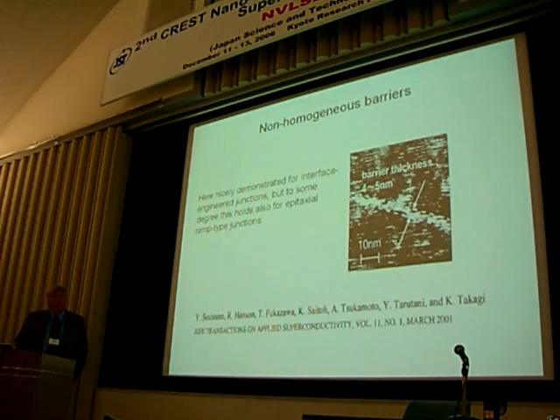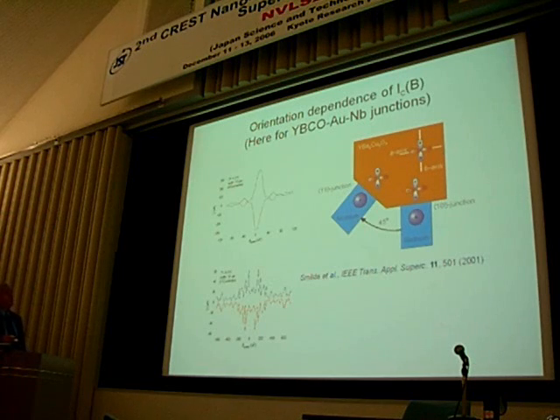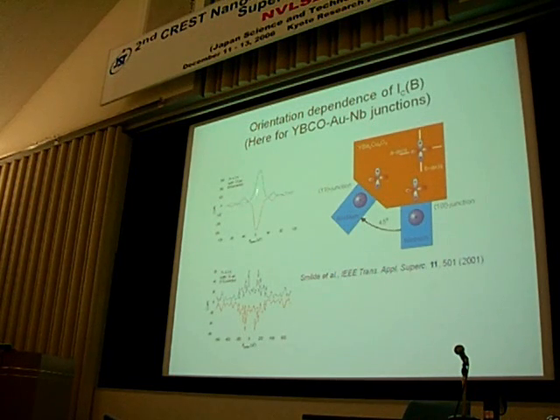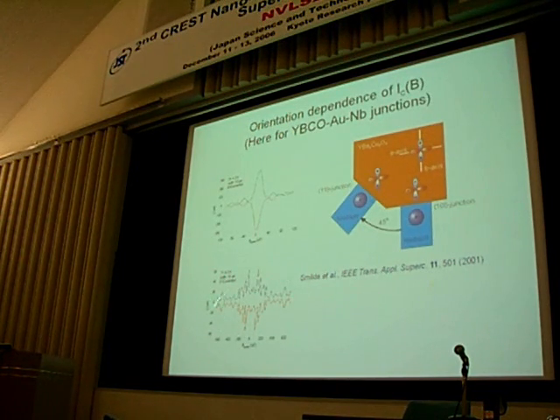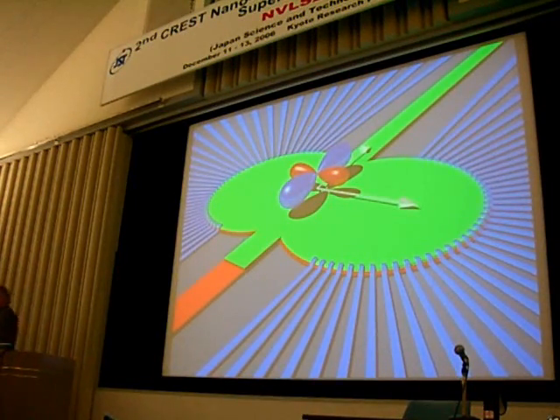What are the difficulties? I've already said the barrier is one. But there is also difficulty because of the direction dependence in the D-wave symmetry. If you have a direct connection you get quite high, very nice tunnel current, and it's very transparent. But if you are 45 degrees apart, it looks very bad. And one can investigate this by looking into the transport through through such structures in different directions.